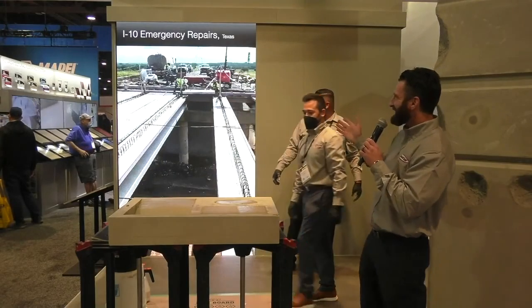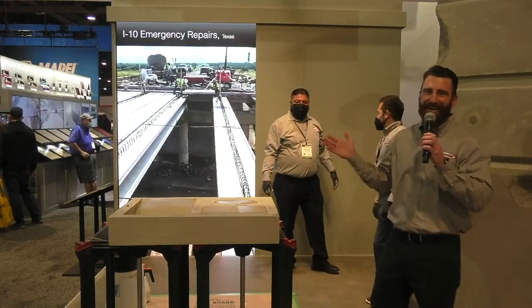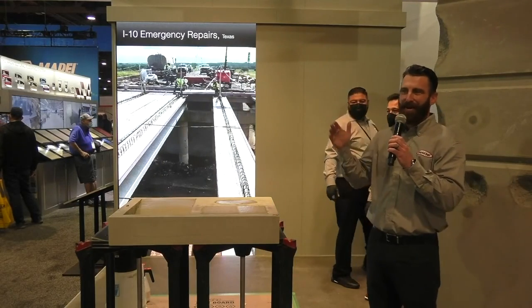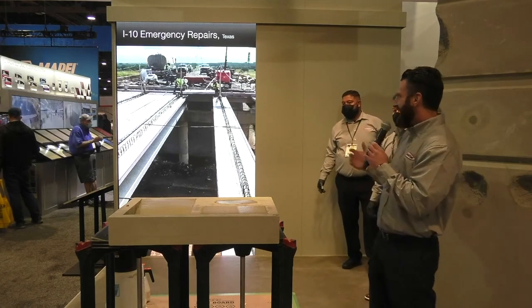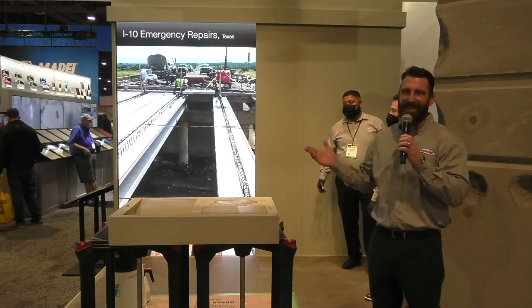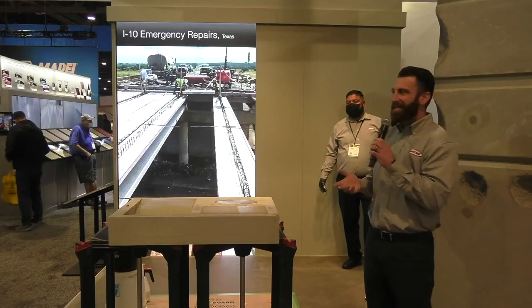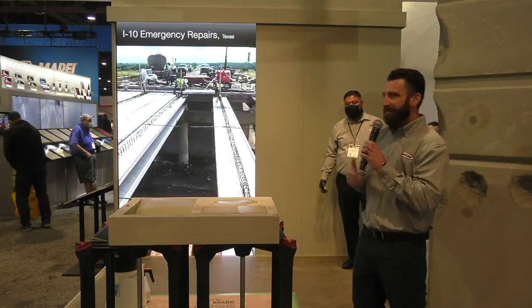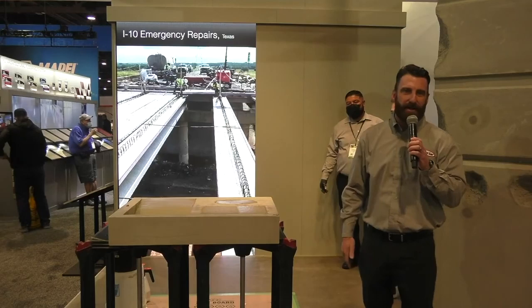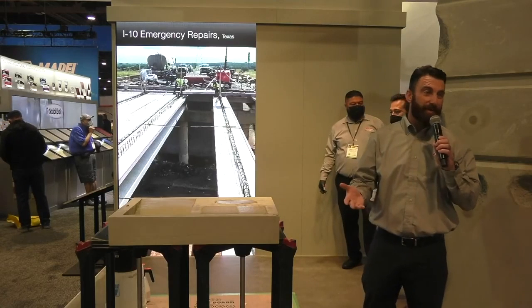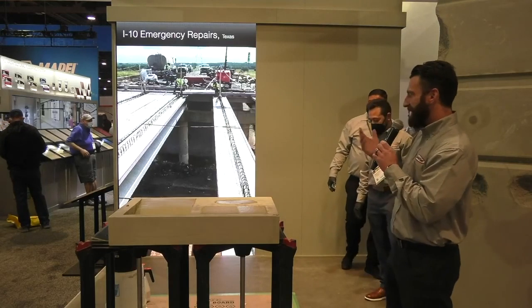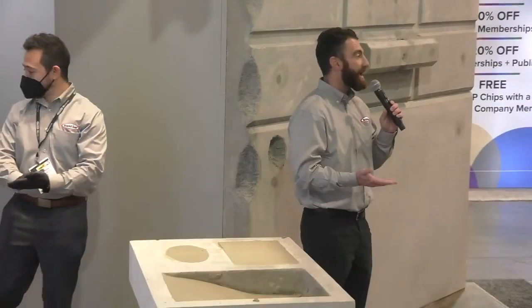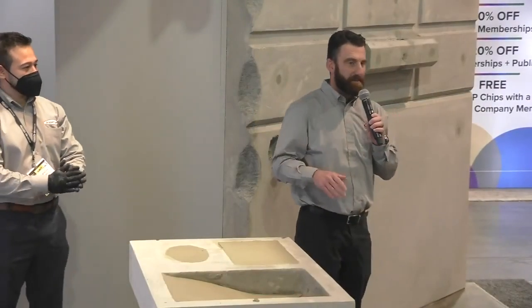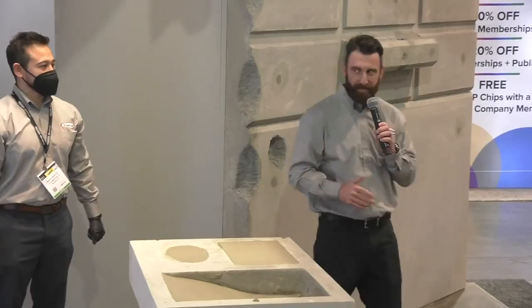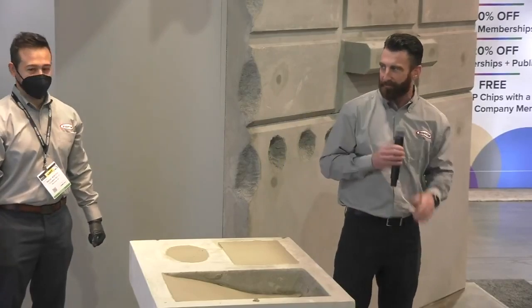And this is the I-10. There was an emergency repair. An oversized tanker took out one of the cross beams on the I-10. And so what the TxDOT needed to do is they needed to replace 10 new pedestals and wait for that to gain strength before they could install the new cross beams. And they wanted to get all that done in 24 hours. And so they were able to use the Rapid Set concrete mix because of the very high early strength. They got the strength of the pedestals. They were able to install the cross beams and open it back up to traffic.